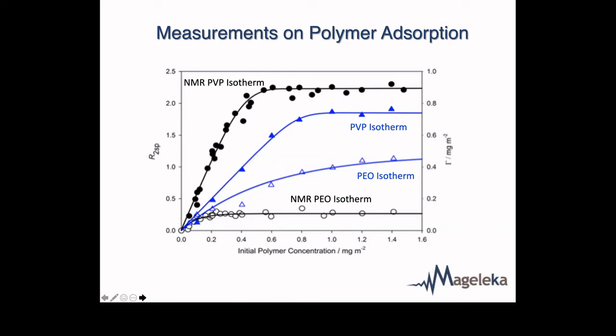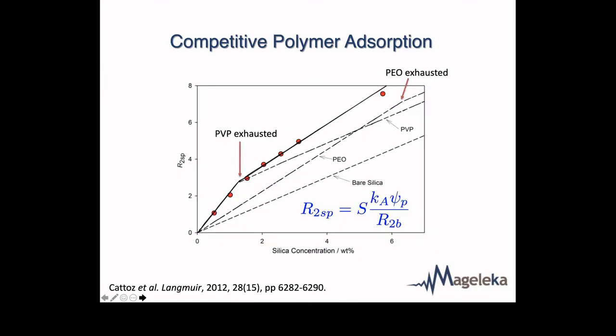In fact, from these experiments, we can actually do a clever experiment. We can absorb PEO onto a surface, then add PVP, polyvinyl pyrrolidone, and it displaces it. Now that's a very useful thing in a complicated dispersion, because if you're stabilizing a particle, you want to know that the stabilizing polymer stays on the surface. You can also challenge an adsorbed layer with different things.